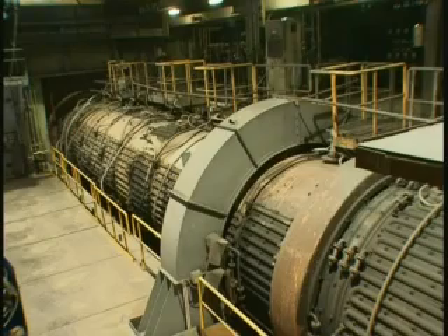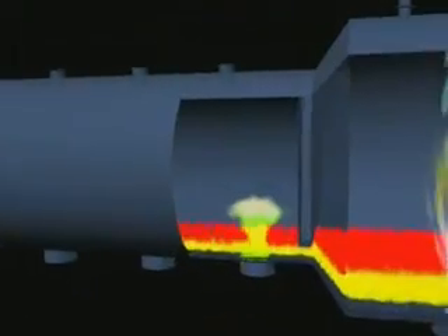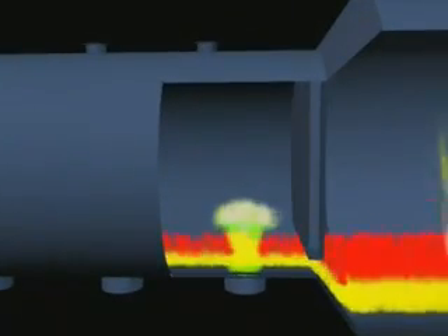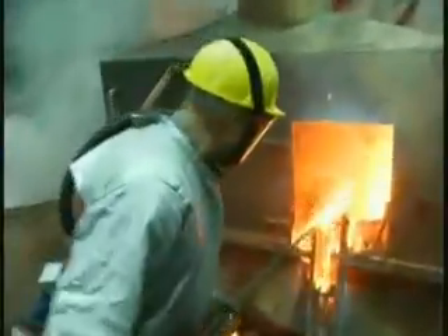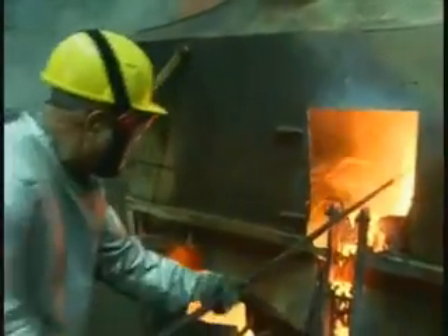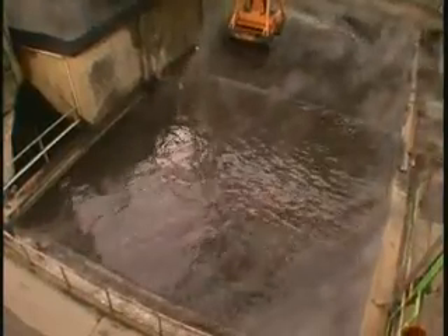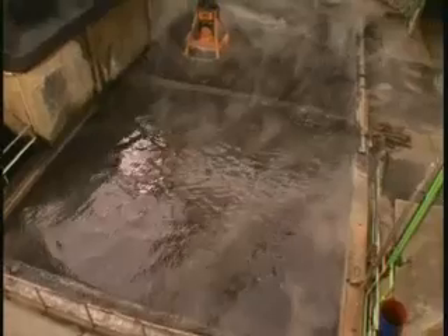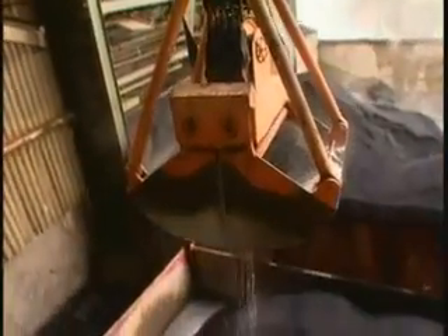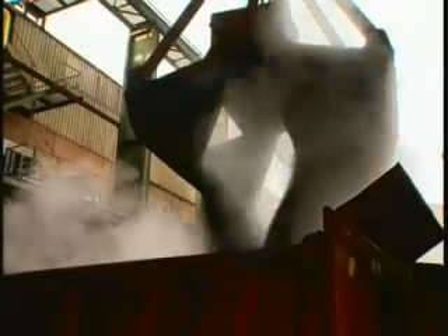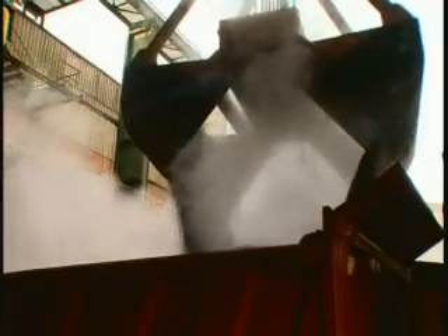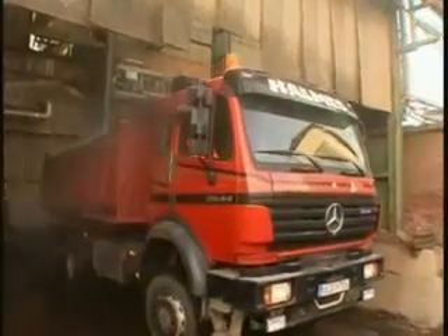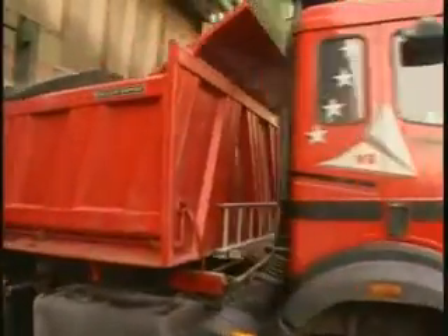The low lead slag is lighter than lead and floats up until it reaches a level where it can be tapped off. This is done at regular intervals. At the same time, samples are taken there for quality checks and for process control. The slag running off is quenched in a strong water jet and solidifies to form granules that look like grains of sand. These are routed to a slag granulating basin. From there, the granulate is removed by trucks for further utilization.